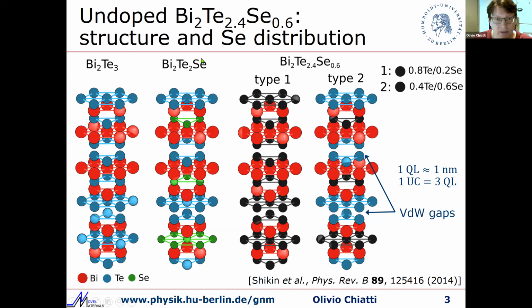Now, when we look at the ternary compound, where we substitute one tellurium atom with one selenium atom, usually the central atomic layer in the quintuple layer is the selenium layer, and the other two layers remain tellurium layers. So what happens if we change the stoichiometry to some non-integer number? The work published in Physical Review B looked at two extreme cases of selenium distribution. In one case, all the selenium stays in the central layer in the quintuple layers with the distribution of 40% tellurium and 60% selenium. The other extreme case is where selenium is distributed through all tellurium layers.